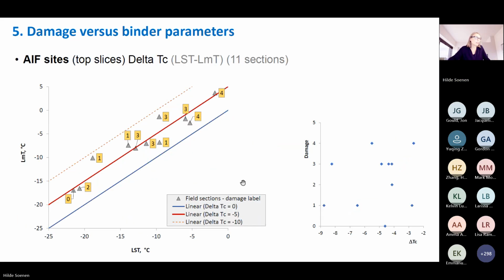So then we did the same thing, but for delta TC. And this is now plotted in a diagram showing the limiting M temperature versus the limiting S temperature. And here you see the number 4, for example, once it is above the critical line and once it is below. There is a 1 above the critical line and some are below. Here is a lot above. So if you now plot damage versus delta TC, you see that there is no correlation that we could find.